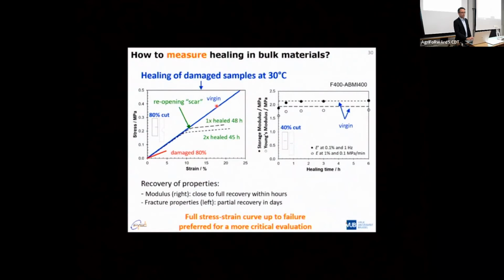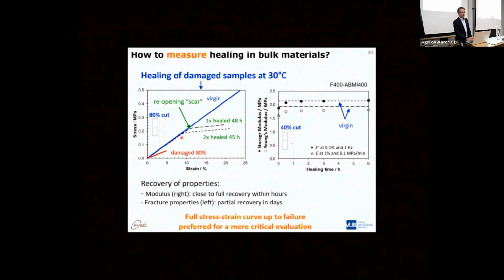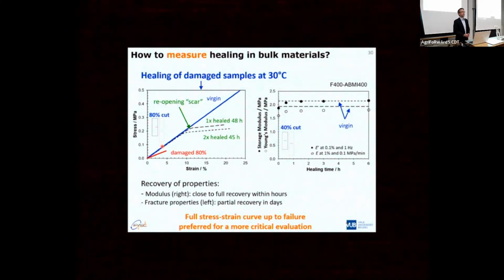This is an evaluation with the virgin material, the damaged material, 80% cut, and then materials that were healed. And you see that the curves over the first 5 to 7% are overlapping. So the Young's modulus at small strains is completely healed. But then you see that the curves start deviating. What is happening is that the scar starts to open and starts to tear apart again. So yes, if you use this system in an application where you only go to 5% of strain, this is fine. It's healed for functionality, but it still takes a lot of time before it's fully healed.